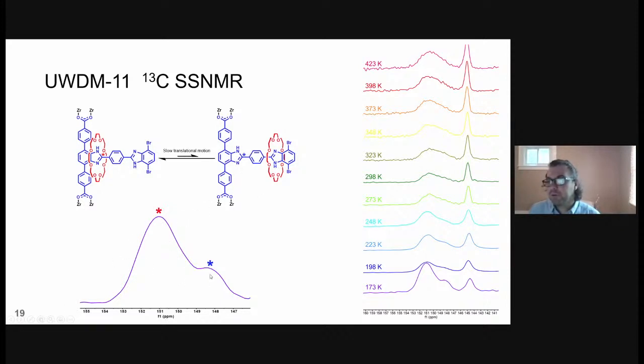As we've got these uneven peak sizes, this is a result of this being a non-degenerate molecular shuttle, and the ring having a high preference for this terphenyl stoppered carbon-13 enriched end. This is in line with what we're seeing in solution for these systems, where these phenyl rings actually stabilize the binding of the crown ether here, as opposed to these bromos at the other end. We can see as we start to warm the sample up, we get coalescence at approximately 273 Kelvin.